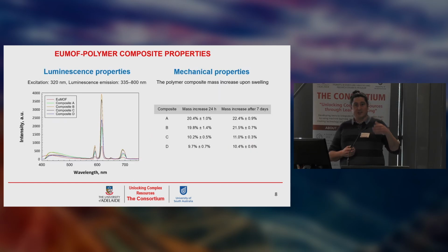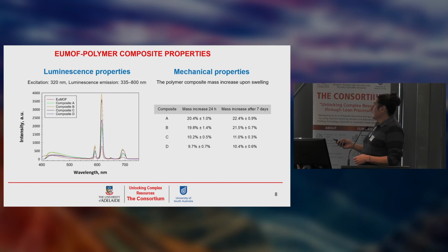So the response of these composites was studied using fluorimetry, and the europium in the MOF will have a luminescence response when it's excited. So excitation of the MOF or the composite at 320 nanometers results in emissions at around 600. So you can see these emissions from the different composites when they're excited at 320 nanometers. And depending on the composite, how it's made, how the MOF is embedded into the polymer network, you get a different response when the MOF is excited.